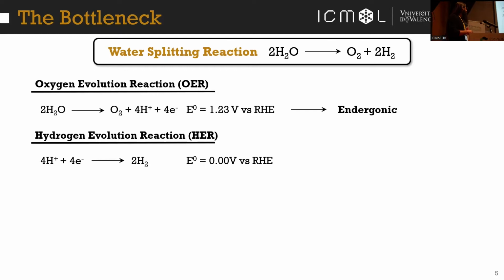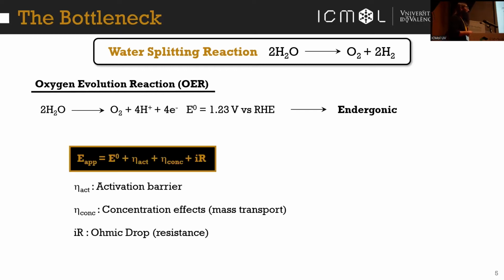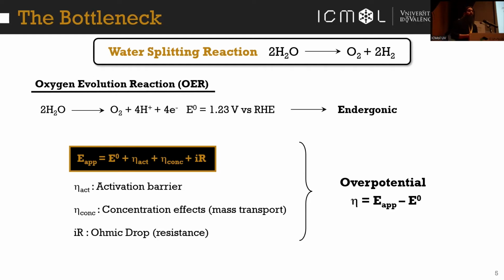Of these 2 reactions, the bottleneck is considered to be the oxygen evolution reaction, because it's a very endergonic reaction. In addition to the thermodynamic potential of water, we need to apply more energy in order to overcome the activation barrier, concentration effects, and ohmic drop. This extra energy is known as the overpotential, and it's basically the extra energy we have to apply on top of the thermodynamic value. In order to reduce this overpotential as much as possible, we need to use a catalyst.